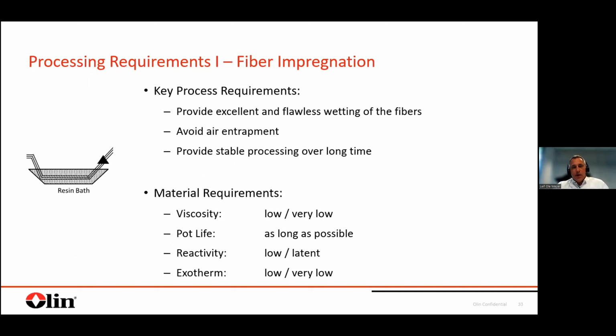And last but not least, we expect this also to run over a relatively long time in a kind of stable process without a lot of need to do corrections. Based on this, the key material requirements for this fiber impregnation step, first and most important, is really the viscosity to achieve very good and excellent wetting, and a high line speed to achieve productivity. Basically, the viscosity needs to be low or even very low. It's really for the wetting. In particular for carbon fibers, the viscosity should be as low as possible.